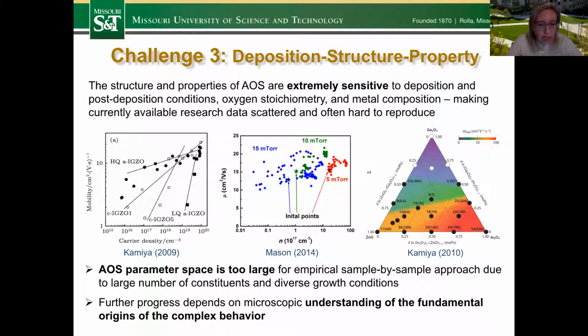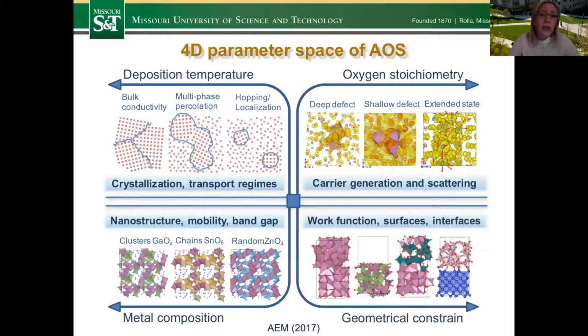So the parameter space is so large for these materials, and again, the growth conditions are so diverse that we really need to develop some microscopic understanding in order to have some predictions, because it is just impossible to do an empirical sample by sample approach. So our goal is to look at different parameters that may control the properties and separate them, and then develop a theoretical model of these materials. Here is the 4-dimensional parameter space for amorphous oxide semiconductors that I will be looking at in this talk.